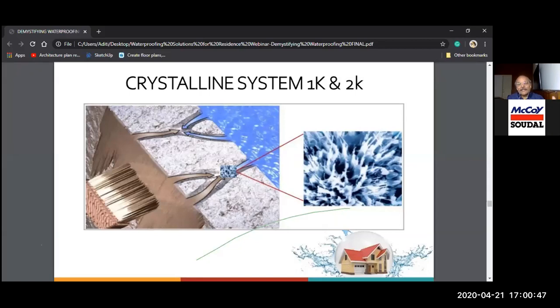Now, once the casting is done, the raft has been casted and the surface is still wet, green, if you sprinkle and broadcast again, maybe 1 to 1.2 kg or 1.5 kg, because the dosage depends from company to company. Different companies have different dosages. So from 1 kg to 1.5 kg, believe me, you're going to have an impregnable waterproof basement. You won't get any water from the raft.